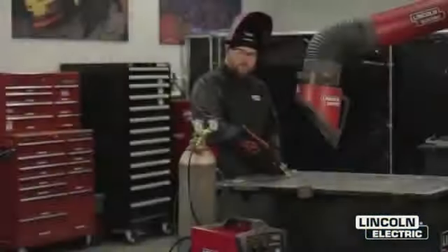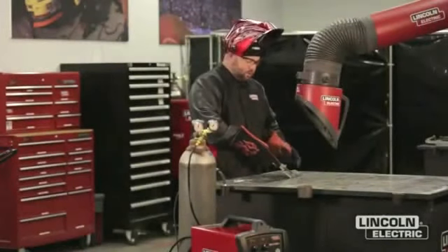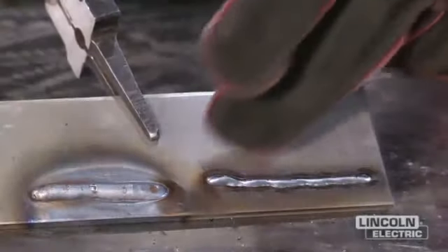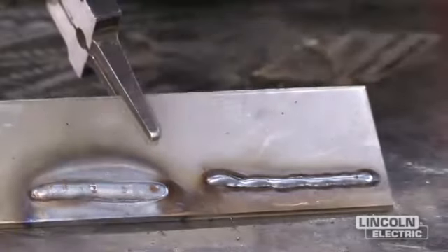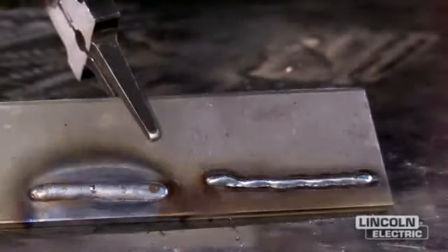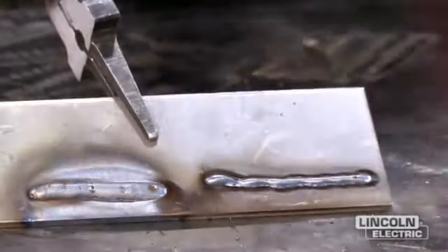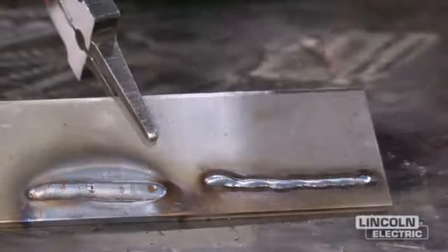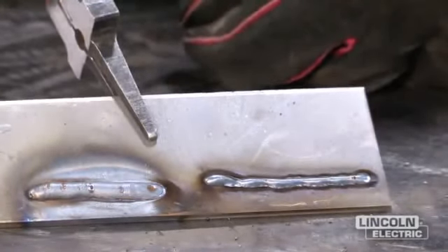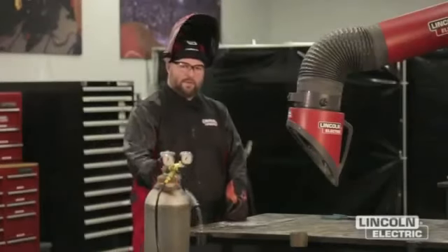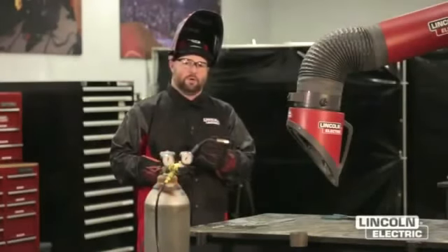So now the last weld we made, our travel speed was too fast. You can see how narrow our weld was, and if you notice the puddle, it was not keeping up with me. So this first one is too slow, and the second weld is too fast. Now we're going to look at the effects of our contact tip to work distance.